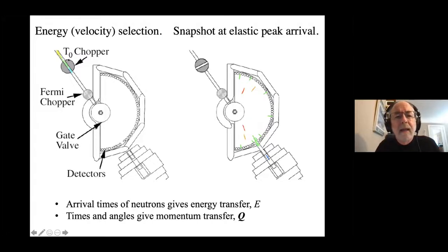And they fly down with kilometer a second velocities, and little spinning cylinders with slots let through the neutrons of a fixed velocity. Let's suppose we let through the green ones and this rainbow of neutron velocities. And they hit the sample, and sometime later we detect them at the detectors. This is all done by timing. And this is where the elastic peak might be hitting the detectors. We get a diffraction pattern in that case, and also a calibration for our energy scale.